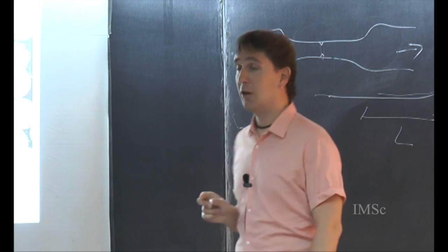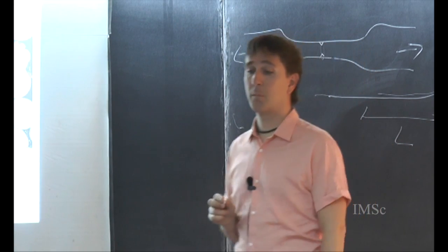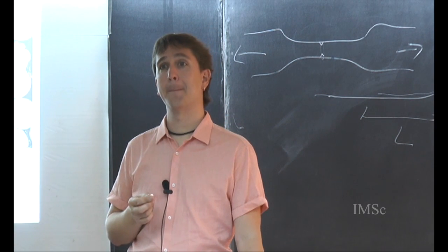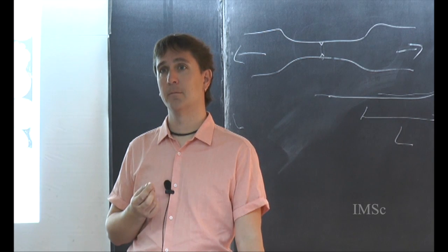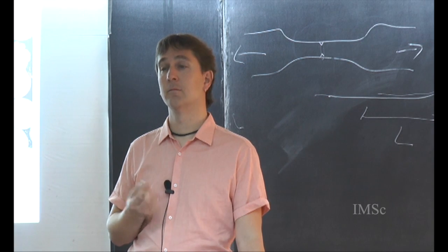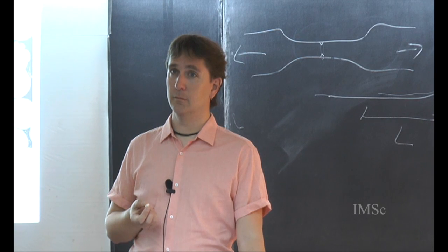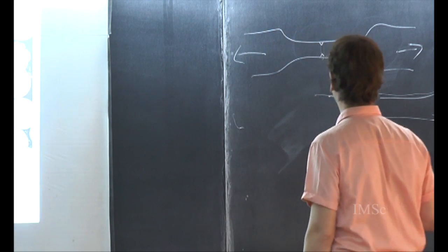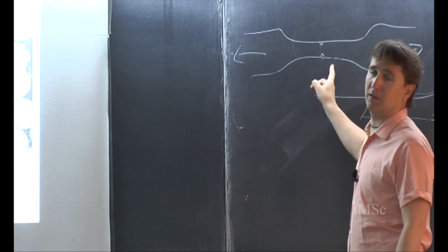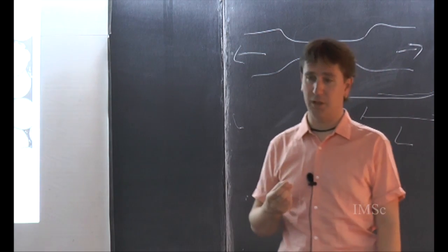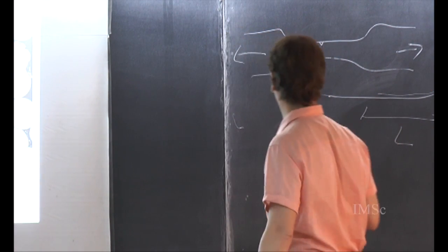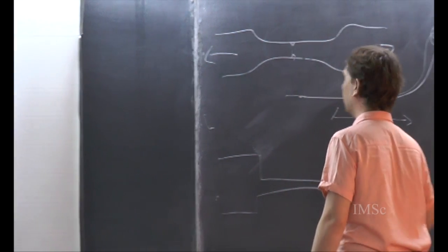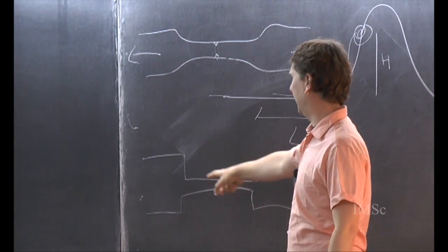In our case, we don't start with any notch. The system chooses the final failure mechanism. In one case you get a very thin neck, and sometimes you get a cavity, and then it eventually breaks. So it should be able to be made in that geometry. We've made things close to this, but not this geometry itself. But there's no reason why it shouldn't be able to be made in that geometry. We made this just as a proof of principle test, not that extreme.